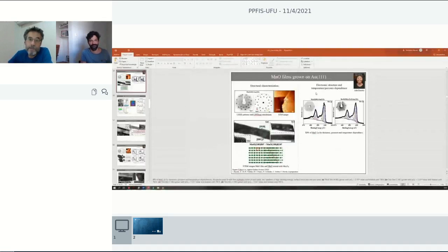Okay. So my initial guess was that the cross-section was larger, but it's more than that. You get more accuracy and you get more information too. For the conventional aluminum source in all labs around the world, you have more cross-section, as you say. But when I showed you that example in the synchrotron, where you try to excite with different energies, so you actually change the cross-section, the sensitivity, it's still a mess, because the peaks are still very broad, and it's very hard to see tiny changes. So it's all this together that brings us to the 2p, from all transition methods, as the peaks that we should analyze.